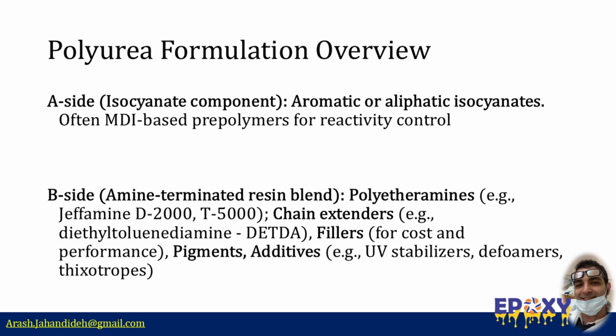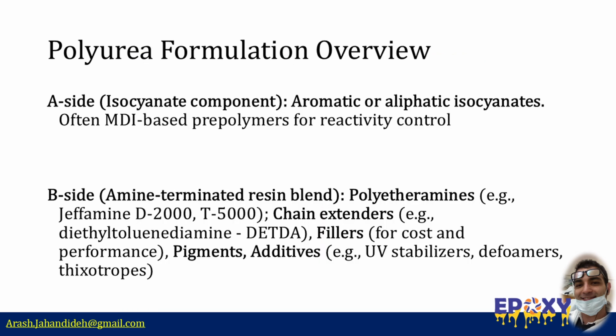Polyurea systems are typically formulated as two-component systems, part A and part B. The A side contains the isocyanate component, which can be aromatic or aliphatic. For better processing and more controlled reactivity, MDI-based prepolymers are commonly used instead of pure MDI. The B side is a blend of amine-terminated resins. These often include polyetheramines such as Jeffamine D2000 or T5000, which determine the backbone flexibility.